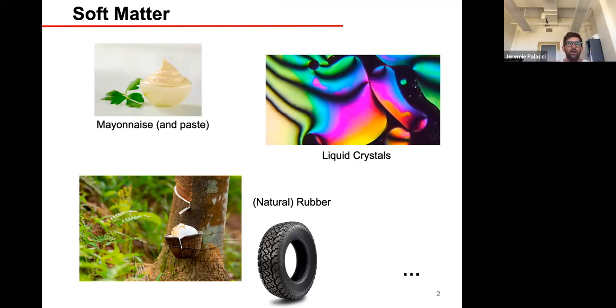So if you now get this sap into a bucket and you leave it in presence of oxygen for a few minutes, the oxygen will react chemically with some of those long polymers in solution, which will bridge. And so now, all of a sudden, instead of having a liquid with long chains, you end up with a liquid enclosed in a network. And so instead of having a gooey and viscous liquid, now you have an elastic solid, which is rubber.